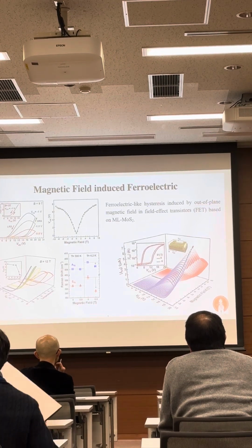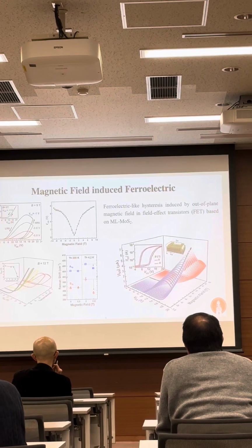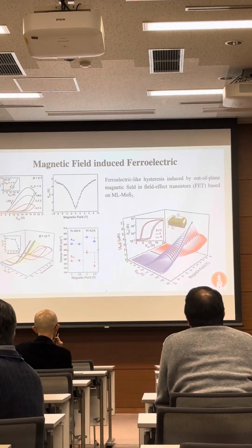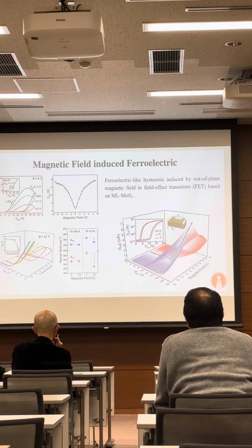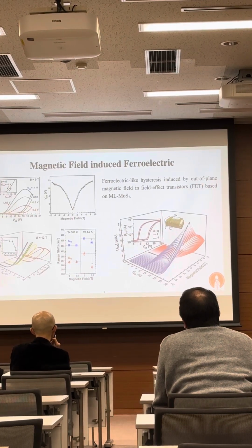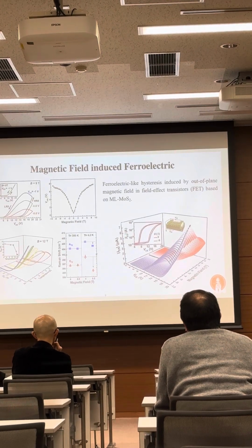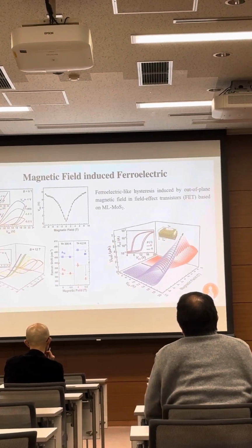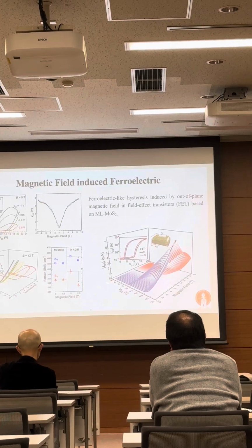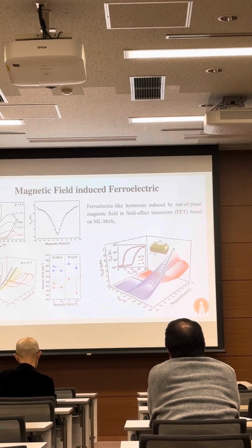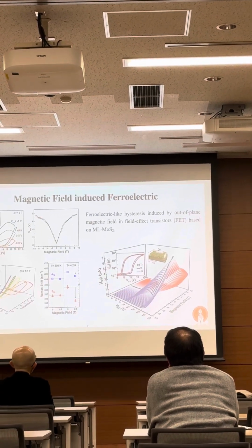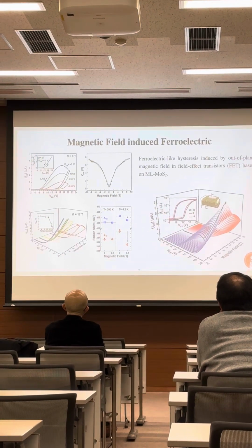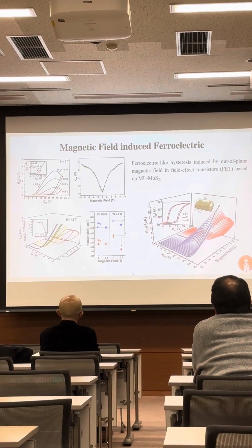As the first figure demonstrates, you can tell that upon applying an out-of-plane magnetic field, for example, 9 Tesla here, a counterclockwise hysteresis loop will emerge from the measurements of the FET device at about 1.8 Kelvin. This hysteresis window will increase as the magnetic field slowly increases and then saturate for larger fields. Moreover, the size of this hysteresis loop will expand as the temperature drops and also saturates around 14 Kelvin. On the other hand, there is no hysteresis loop present at zero applied field or at any temperature above 20 Kelvin.